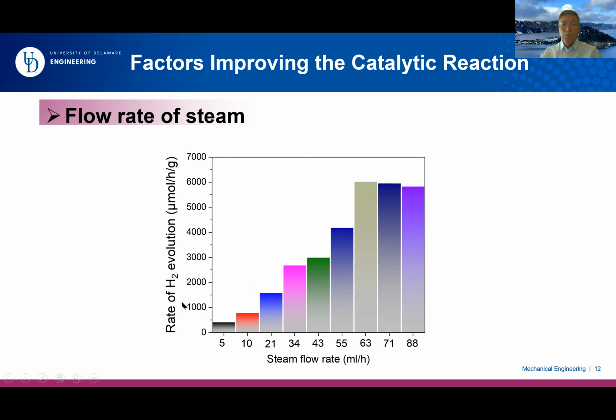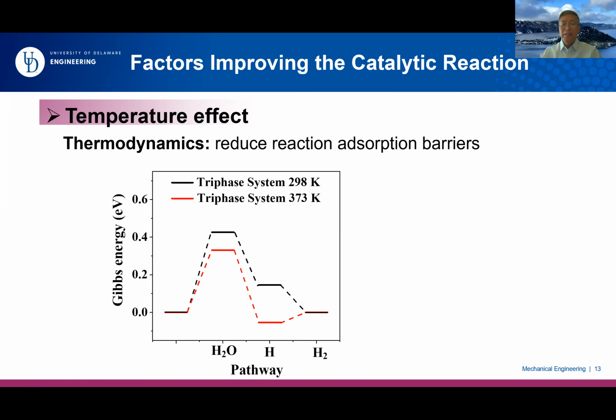So this is the rate of hydrogen evolution as a function of steam flow rate. You can see that as the flow rate increases, the hydrogen production rate also increases. However, it will saturate once it reaches a certain speed. For example, at about 80 milliliters per hour, we pretty much reach the optimized hydrogen evolution rate. And other factors you can easily imagine, like the temperature effect.